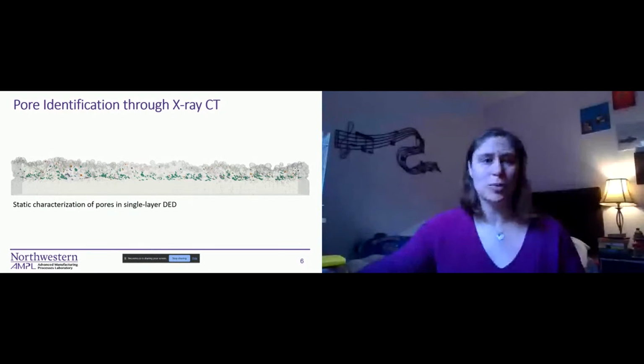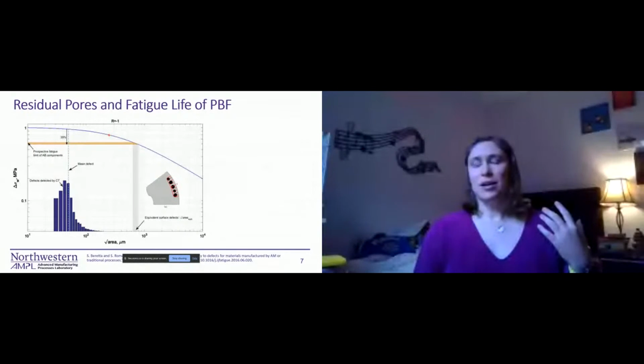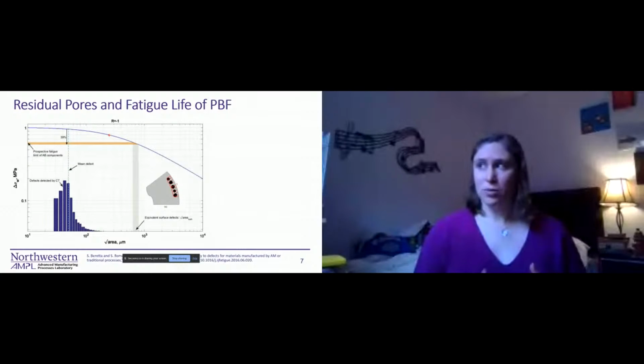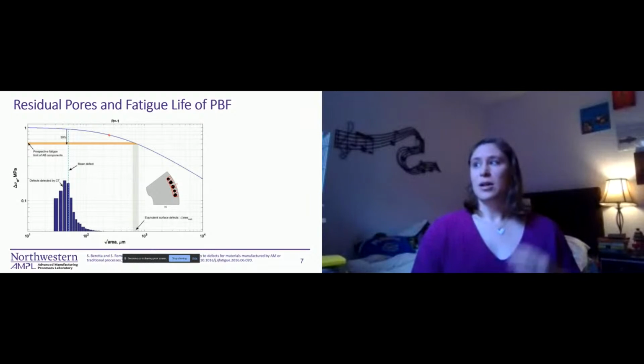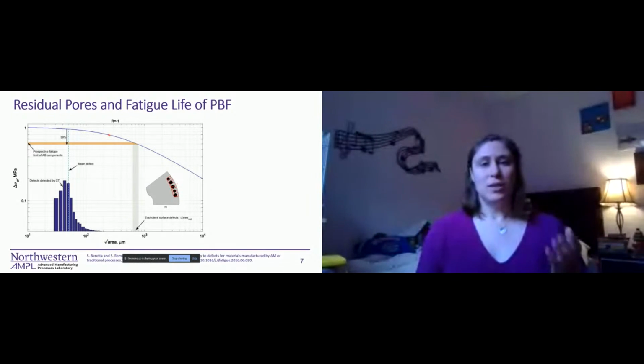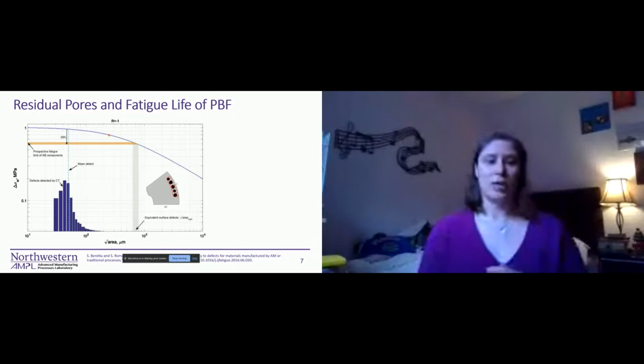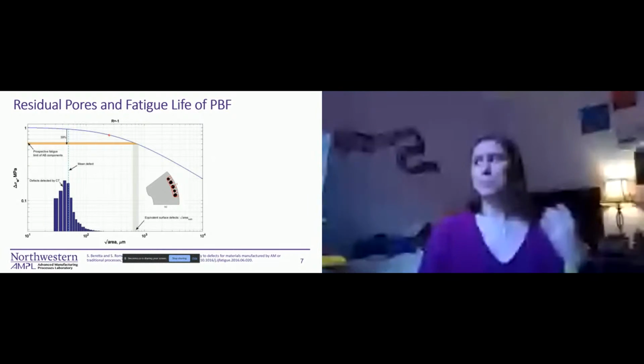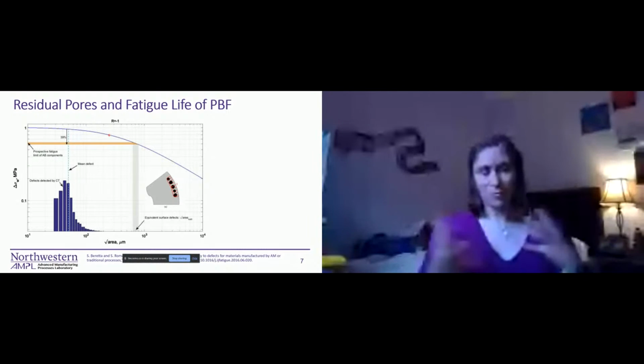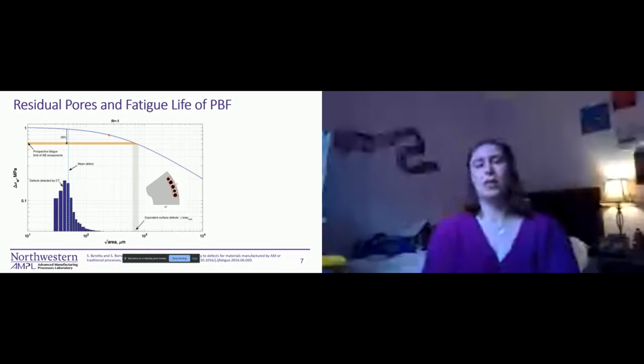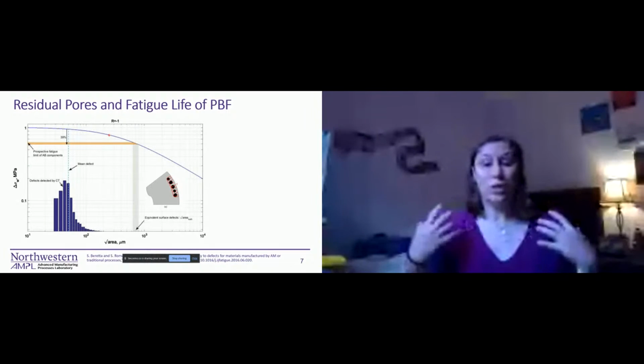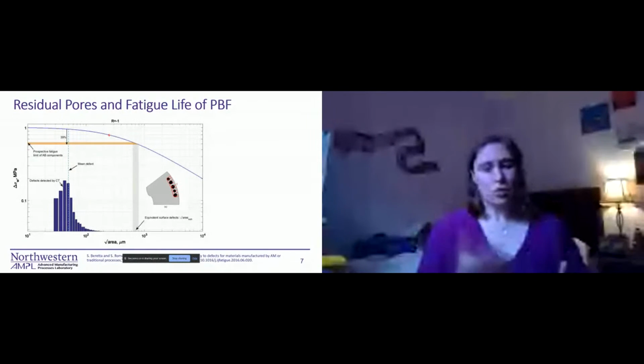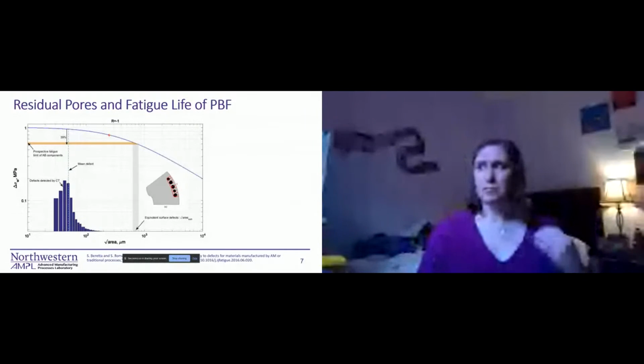So why do we care about pores so much? Specifically, the pores have to be hipped or the parts have to be inspected in order for them to be used. It would be better if the pores were mitigated or controlled to an extent. They also affect the fatigue life of the part. If you have subsurface pores, it will actually greatly reduce the fatigue life. Since I've mainly worked with defect formation in DED, I was looking into ways of how we can mitigate this. How can we either control or change the shape of pores and how many there are to target better performing materials.